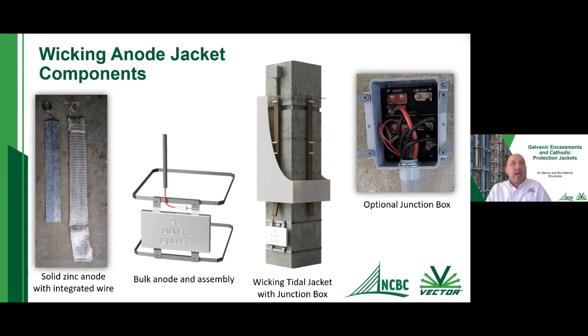And then, as I mentioned, you can have an optional junction box. And so you can see in here, the junction box, there's a shunt. That's basically just a low resistance resistor. So you can go in and measure the voltage across this resistor, and then you can actually calculate the amount of current that your cathodic protection jacket system is producing. As well, you can see a link bar. Basically, that's just a mechanical switch. That's what actually energizes or turns your jacket system on. And then there's a number of red wires and black wires. Red wires being our anode wires, either from the bulk anode or from the Tidal Plus anodes. And then the black wires are all structure wires, rebar wires.